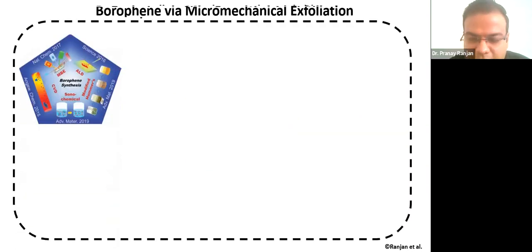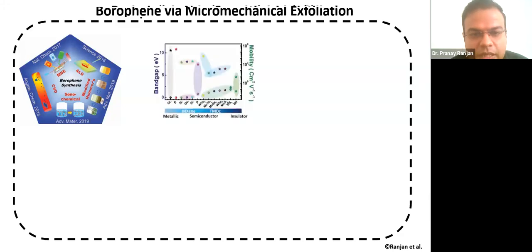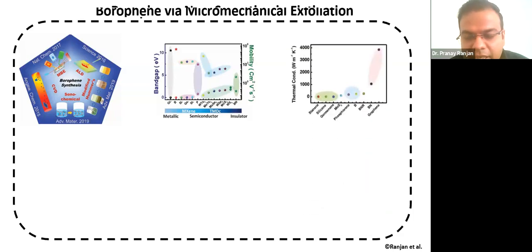Later on, we tried to summarize all the synthesis techniques in the market, and what we found is that out of the 5 techniques, 3 have been given by us. And we are the only ones in the world who present this freestanding borophene, and we started the applications of borophene. Otherwise, with the other techniques, only the intrinsic properties of borophene are talked about. You cannot implement them in real-life examples. Then we summarized the band gap and mobility, which we talked about earlier, as well as the thermal conductivity, where we found that borophene has a very bad thermal conductivity. It's not as good as other 2D metals.